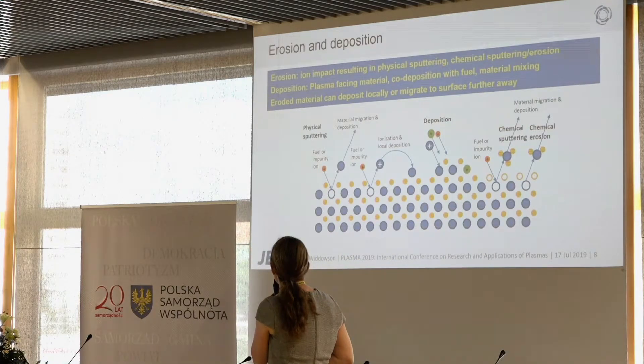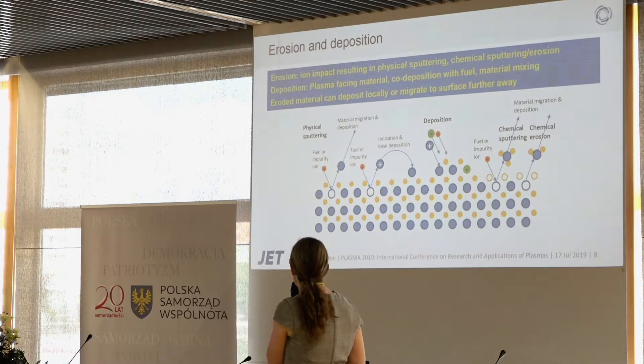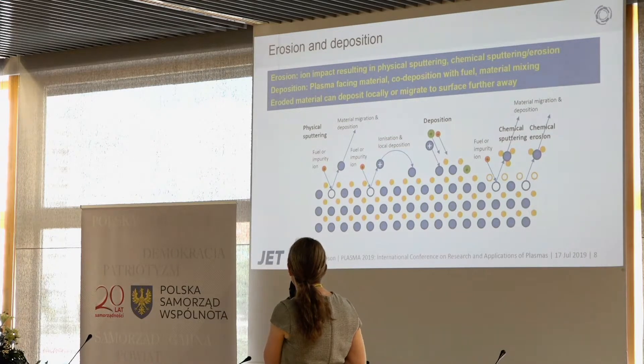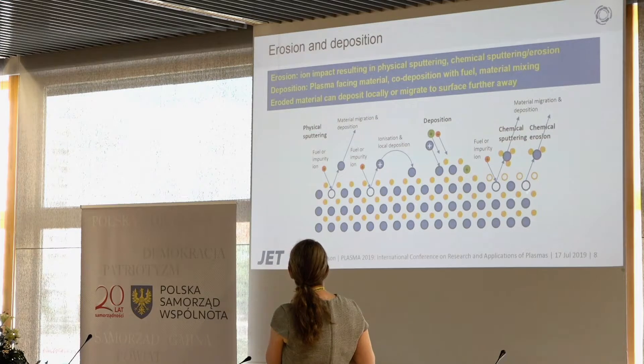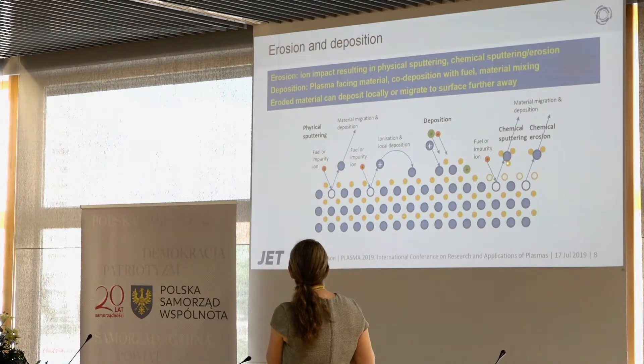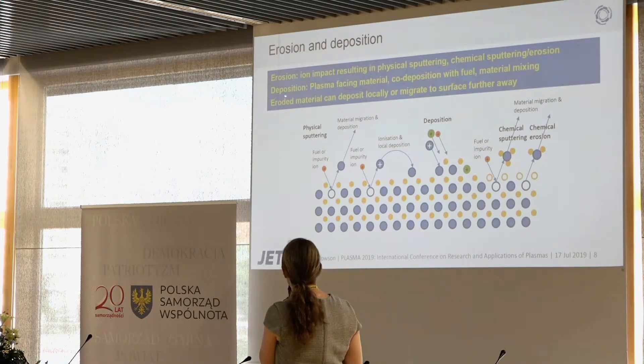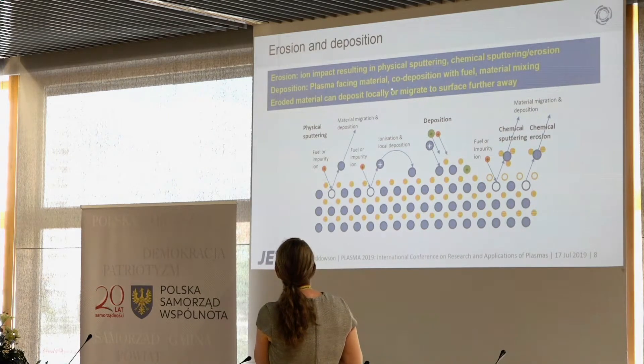Starting with material erosion: material is eroded by incoming atoms through physical sputtering, where fuel or impurity ions knock out material from the plasma-facing wall. We can also have chemical processes whereby fuel ions form hydrogen compounds. Then we have deposition — what's eroded or what comes from the plasma can be deposited — and we get co-deposition with fuel and also material mixing with other elements.